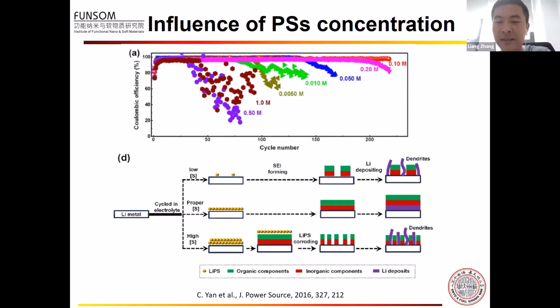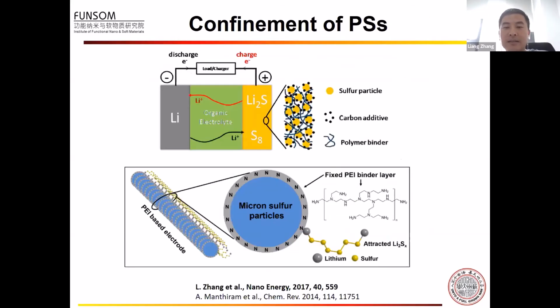So the question is, is there any method that we can control the dissolution of the lithium polysulfide in the electrolyte? And the answer is yes. If we look at the structure of a lithium-sulfur battery, one very important component is the polymer binder, which is used to glue the sulfur particle and the carbon additive. For the commercial binder, we usually use PVDF. However, PVDF has only a weak chemical interaction with the lithium polysulfide. Therefore, it cannot prevent the dissolution of the polysulfide.